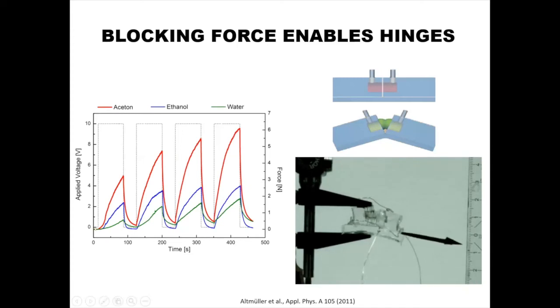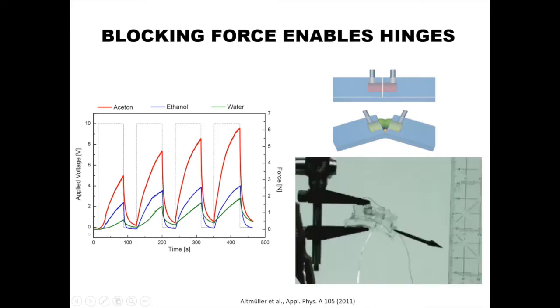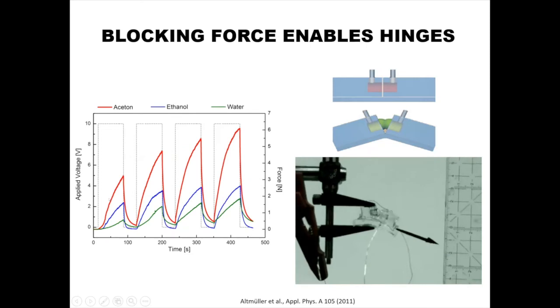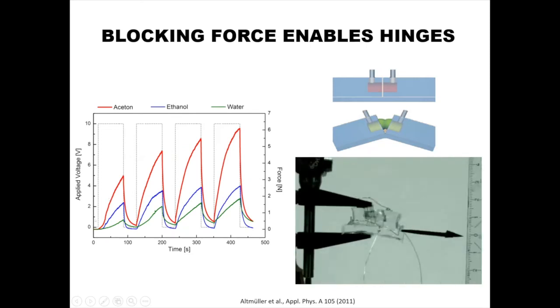What was interesting to us, and what we did not expect, if you look here, we apply a voltage of about 10 volts. We have this 100 ohm resistor. And what we obtain, we use different low boiling point liquids like acetone, ethanol, and water.